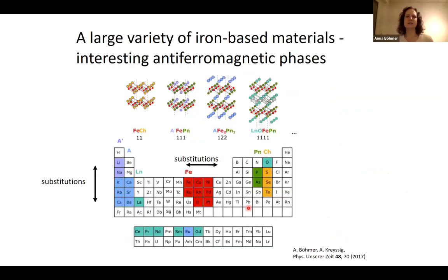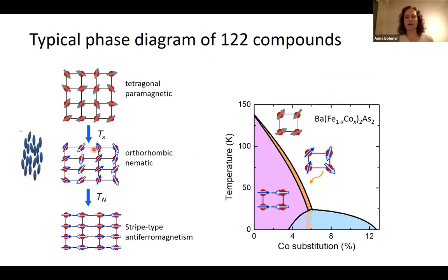It always is interesting and encouraging to remind ourselves that with the iron-based materials, we have a lot of free phase space on the material side as well. Once we can play with substitutions, we can do many things. And I don't need to remind this community of the typical phase diagram of the 122 compounds. We've just seen that, with a stripe-type magnetic order, a nematic phase, and a superconducting dome. That's what we always have in the back of our minds.